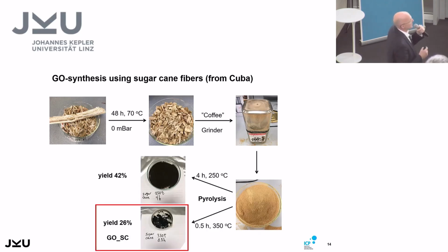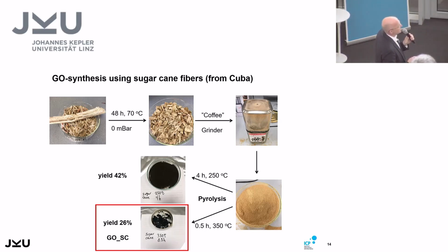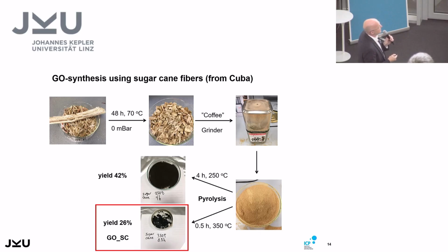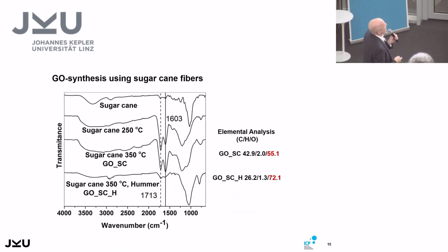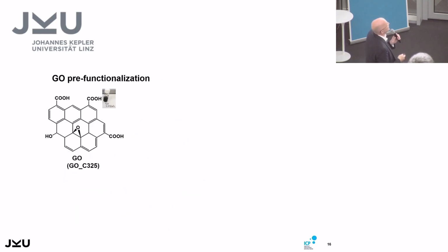And in the next step, it underwent a pyrolysis. First of all, 250 degrees, 4 hours. The yield is higher, as we saw in the result, but it still contains some fiber residues. But at much higher temperatures, shorter times, we observed less yield, but much better and more fine powders, so to speak. So we lost all these fibers. And in the end, again, a short look on the carbonyl functionalities. They also here show us that we have enough carboxy functionalities, not going too much into detail.